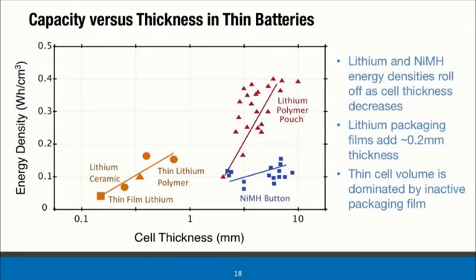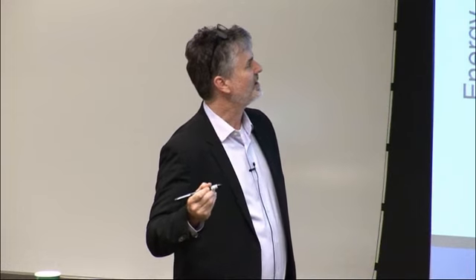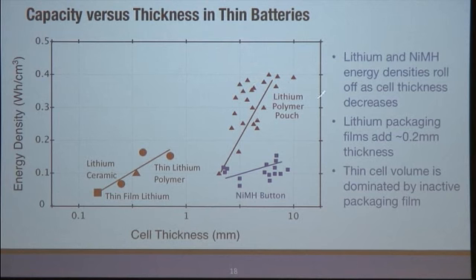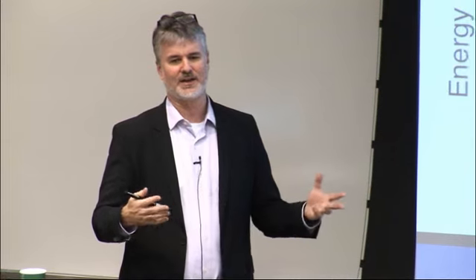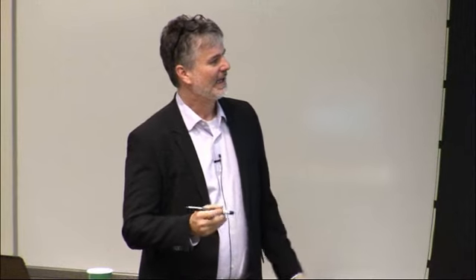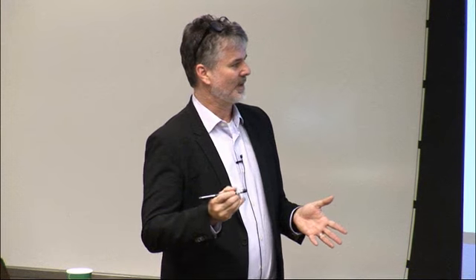And ultimately, the story comparing this to a lithium battery, this is energy density versus cell thickness. The actual energy density that you see advertised for your Samsung Galaxies and iPhones is up here in the 400 watt-hours per liter or 400 milliwatt-hours per cubic centimeter. But as they get thinner, it drops off dramatically. The reason why is packaging. Because regardless of the cell, you still have to prevent the air, water, and moisture from getting in. And in fact, the smaller the cell is, the higher the surface to volume is. So the more packaging per unit volume you need. And as you get very thin, you actually end up with no space for battery anymore.